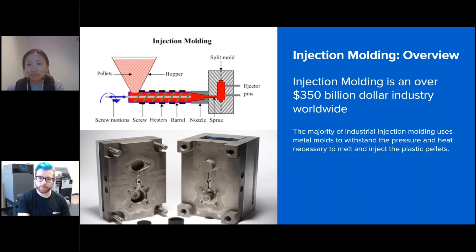Even if you've never sent a part to get injection molded, you've absolutely used a part that was injection molded. It is the industry standard and has been the go-to solution for making production parts for decades. The process starts with a CAD model used to make a negative — typically out of metal via subtractive manufacturing by a CNC machine. This is referred to as the tooling process. This mold is then loaded into the injection unit, which consists of a hopper filled with plastic pellets that feed into a heated barrel, applying pressure and compressing the now-melting material. The molten plastic is pushed into the mold until completely filled, then the mold is removed and allowed to cool so the plastic part can be retrieved, and this repeats until the desired amount of parts is reached.